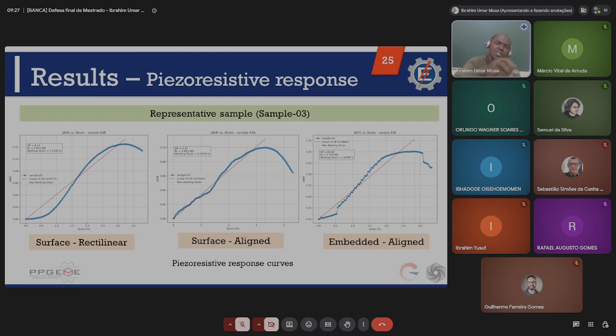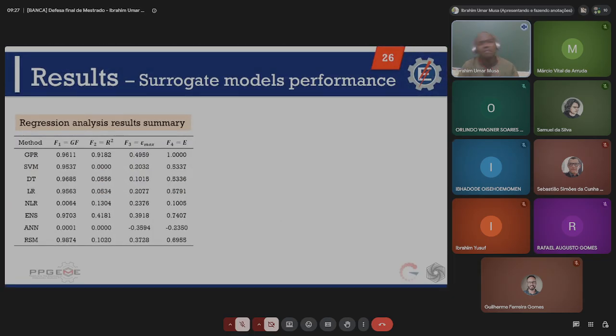They used this data as extracted from these particular curves. And now we have the performance of the regressors during the development of the meta model, the surrogate models, and we can see that for the gauge factor, the response surface methodology performed better, while for the remaining, the GPR regressor appeared to be the best.